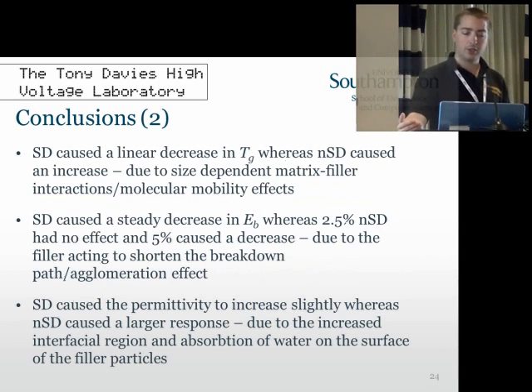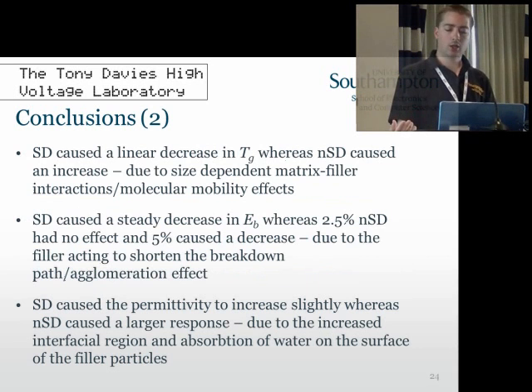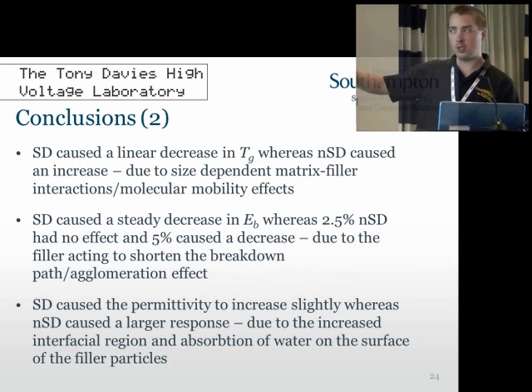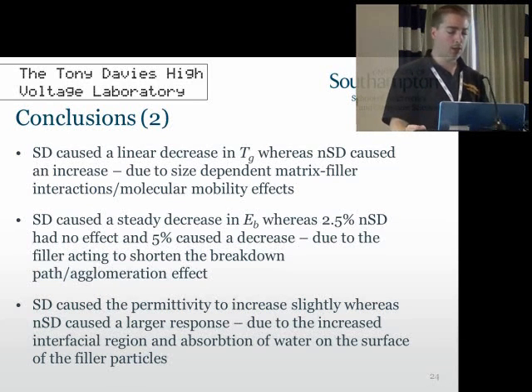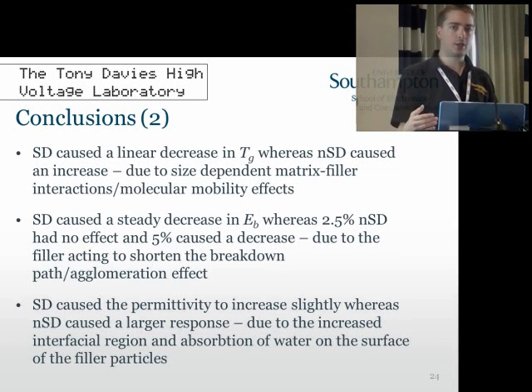From this, we saw that the micro silicon dioxide caused a decrease in the Tg, just a linear decrease, whereas when we added the nano filler, we actually saw a large increase, so a curve towards the higher end. This was due to the dependence of the matrix-filler interactions, so it's just a molecular mobility effect.